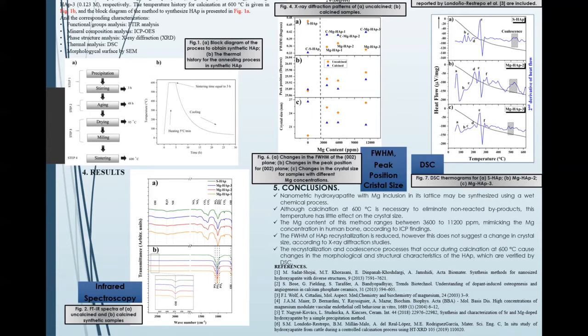Figure 6C shows the calculation of the crystal size by Scherrer equation. According to this figure, the crystal size of the pure hydroxyapatite without magnesium decreases after calcination. But Scherrer's equation does not consider the crystallinity quality, and a combined effect is thus present in the studied samples after calcination. In resume, the recrystallization produced a decrease of the FWHM that does not imply a change in the crystal size.